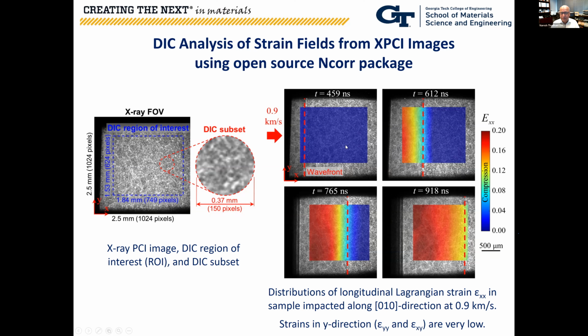And what you're seeing is the strain front, literally mapping the propagation of that shock front moving under conditions of uniaxial strain. You can see that in this scenario, the only thing that you have is the normal strain epsilon xx. There is negligible lateral strain epsilon yy, and barely any shear strain as well.